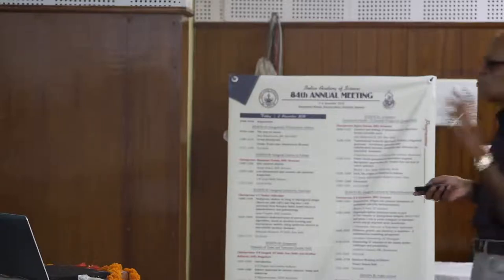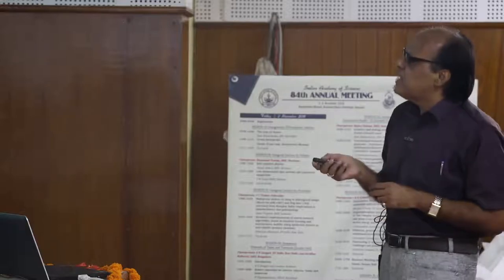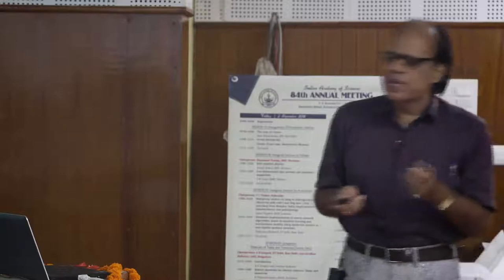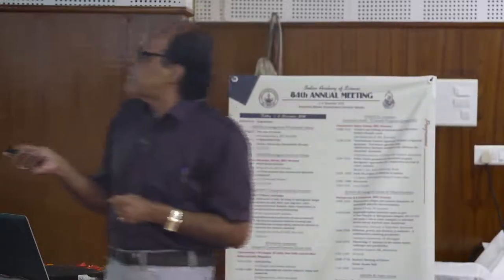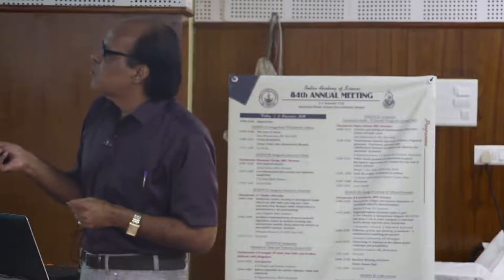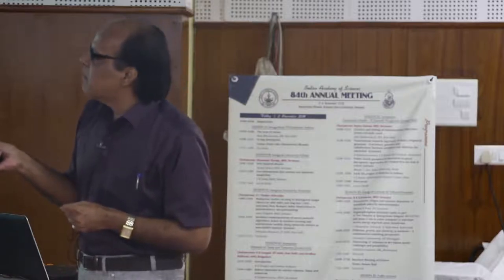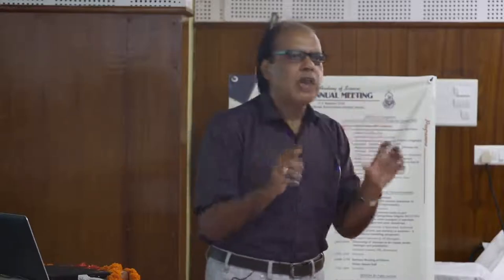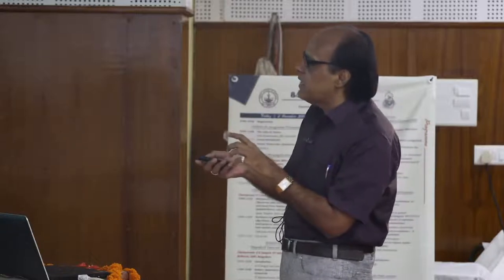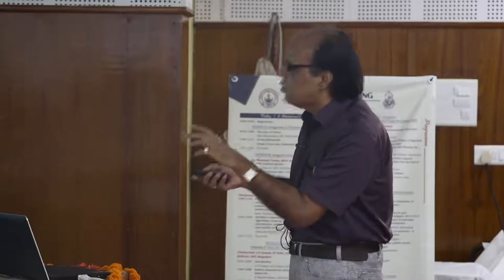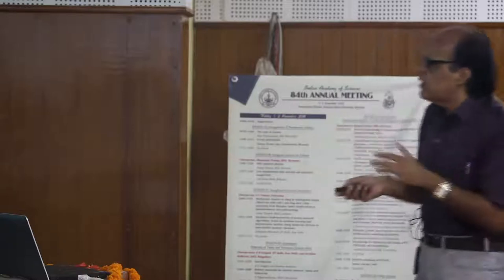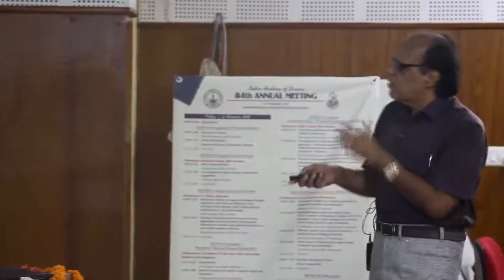We have to fine-tune the microstructure and so on — long way to go. Very recently we worked with SrTiO3, which is an incipient ferroelectric. We replace 2x of titanium by x of iron and x of tantalum. Iron is trivalent and tantalum is pentavalent, so this combination ensures we don't disturb the anionic sublattice at all — we just play with the cationic sublattice. By introducing an optimum degree of disorder among three cations at the B-site and optimum local distortion, we could convert this material into a lead-free relaxor material.